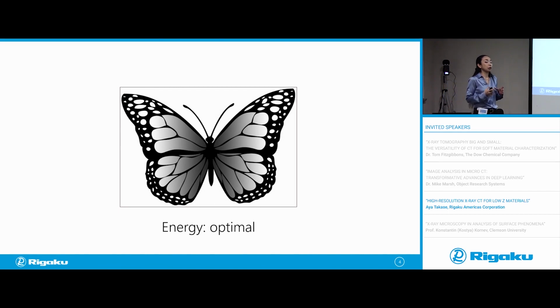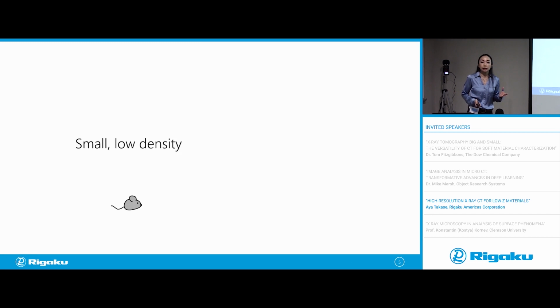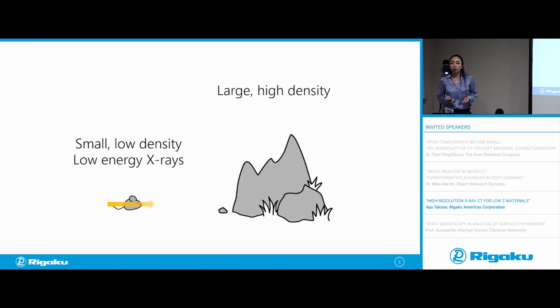Now, in terms of picking the right energy to see whatever sample you're trying to image, the general rule of thumb is that when you have a small and low density sample, you want to use low energy X-rays. This is to make sure that at least some of the X-rays are absorbed by this not really absorbing sample. And if you have a large and/or high density sample, you want to use high energy X-rays because you have to make sure that at least some of it goes through the sample. So that's the rule of thumb. And we're talking about low Z material imaging, so we need to use low energy X-rays.